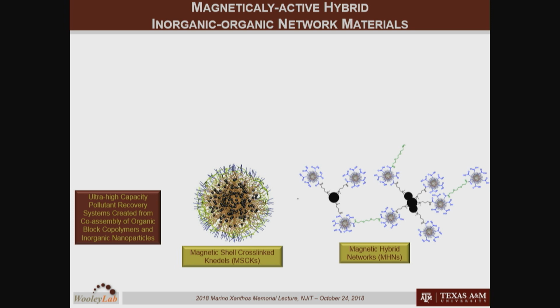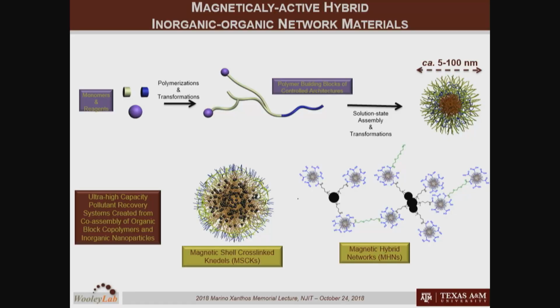in sort of what we call a network approach. And these are called magnetic hybrid networks, whereas these are magnetic shell cross-linked Knedel-like nanoparticles. And Knedel is a Polish word for dumpling. So these have a core shell morphology, whereas these are more like a network structure. And each of these is accessed by a similar synthetic route. We start from small molecules and connect them together into polymers, where those polymers are programmed to undergo supramolecular assembly when they're placed into water to form multimolecular micellar aggregates. And then we can conduct, say, reactions to stabilize those assemblies. So that can give something that's called a shell cross-linked Knedel-like nanoparticle.